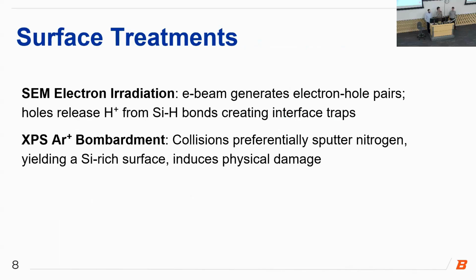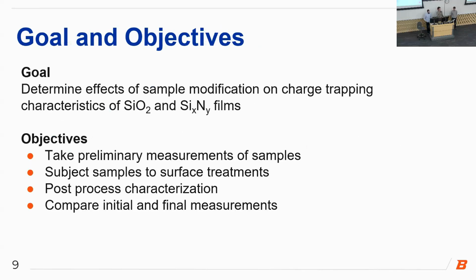To treat our samples, we used two methods. We used electron irradiation with an SEM. This E-beam generates electron hole pairs, releasing hydrogen from silicon-hydrogen bonds, creating more silicon dangling bonds. We also used argon bombardment via an XPS instrument, and these argon collisions preferentially sputter nitrogen, yielding a silicon-rich surface, inducing heavier physical damage. So the goal of this project was to determine the effects of sample modification on charge trapping characteristics of both the silicon oxide and silicon nitride films.